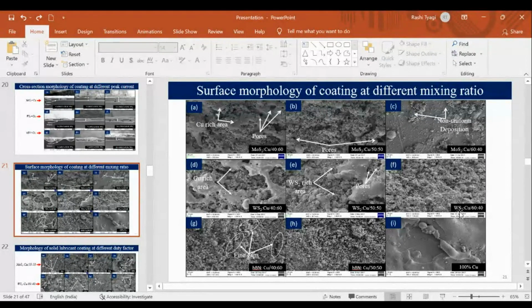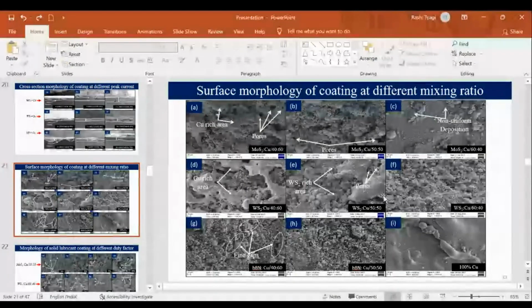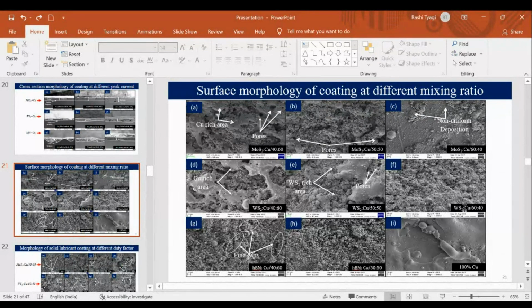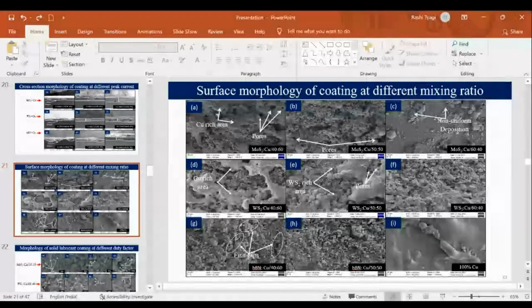For WS2 copper coating, an increase in WS2 percentage helps in reducing the pores. There is a high number of pores at a low amount of WS2 in the coating, but a very low number of pores at the WS2 60:40 coating, because the WS2 percentage is higher. Similarly, for hBN copper coating, it is observed that when the hBN percentage increases to 50:50, a very low amount of gaps and defects is observed in this coating. This is the image showing the process when we are using 100% copper. It means a complete copper coating.